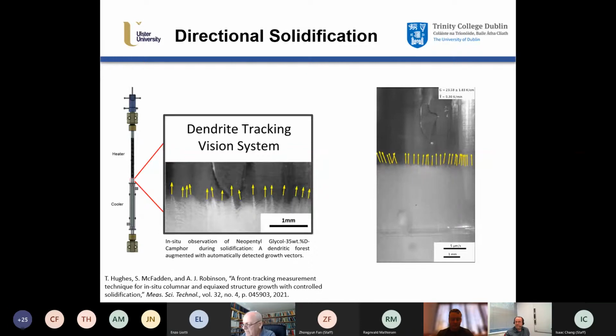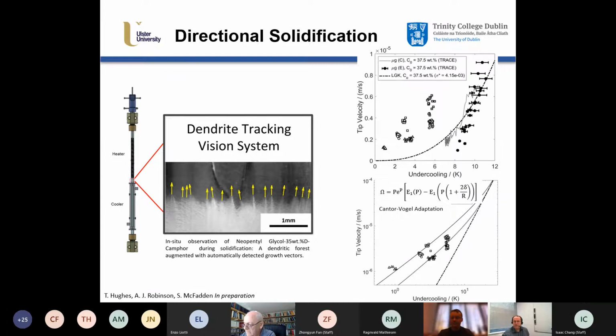There you see a thermocouple within the sample, and eventually it's going to come up and you will see that it gives you a reasonable estimate of the temperature at the tips as it reaches them. The best analogy I can give for this work is that we're no longer just identifying select dendrites as being representative of the growth, but we're trying to analyze the entire forest of dendrites. What did we do with this?